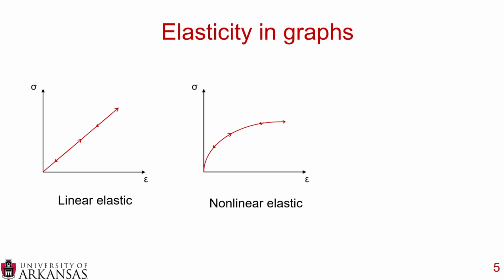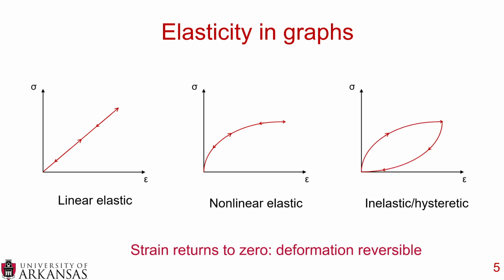You have nonlinear elastic materials where, again, you apply some sort of stress and you measure a strain. It tracks on the same path going up and down, but it's not a straight line. So it's a nonlinear elastic material. And then we have a concept called inelastic or hysteresis. I apologize. And that's where you load it on one path, it unloads on the other path. But the most important thing to notice here, in elasticity, the strain always returns to zero. Any sort of deformation that you put on the sample goes back after you've taken the load off. So all of the strains start at zero, and they all return to zero at the end.